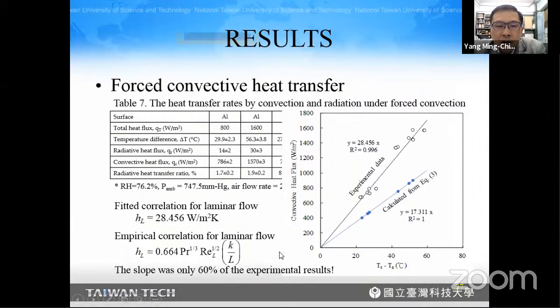And we also plot the result to compare with our experimental result and observe that this calculated result is only about 60% of the experimental result, possibly because there is some turbulent flow during measurement, which will increase the heat transfer.